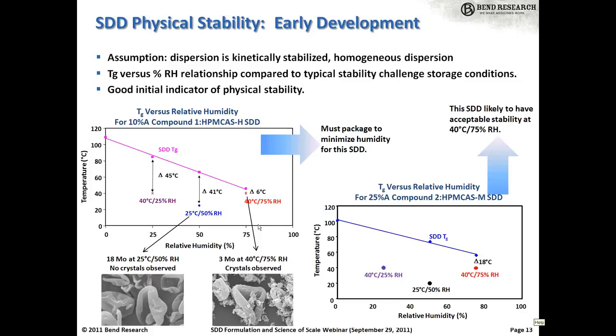So in this rule of thumb analysis, you're measuring glass transition temperature as a function of humidity, and then comparing that to key accelerated storage conditions like the ICH condition. In the example on the left, you measure glass transition temperature using modulated DSC as a function of humidity and compare that to storage conditions. The most aggressive ICH condition is 40 C, 75% humidity. At 75% humidity, you have a Tg of 46 degrees, so there's only a separation of 6 degrees between the Tg and the storage temperature. You'd really like to see ideally a 20-degree separation, or at least a 10 or 15-degree separation. So the prediction here would be that you are likely to have high mobility at this condition and ultimately nucleation and crystallization.